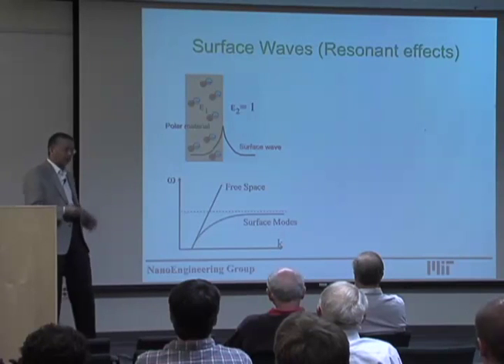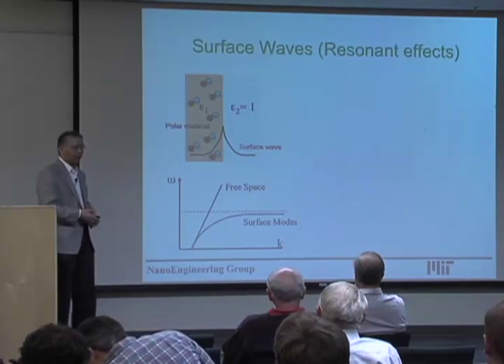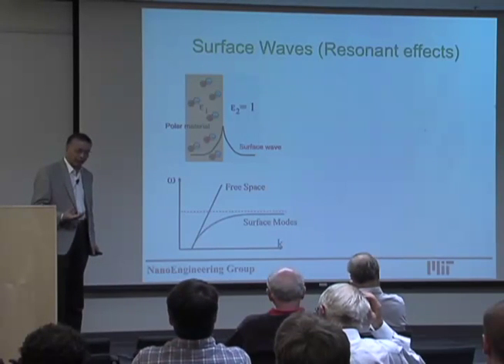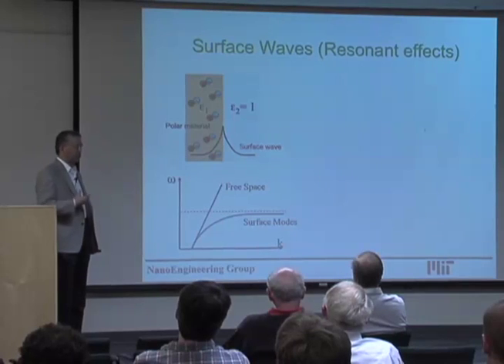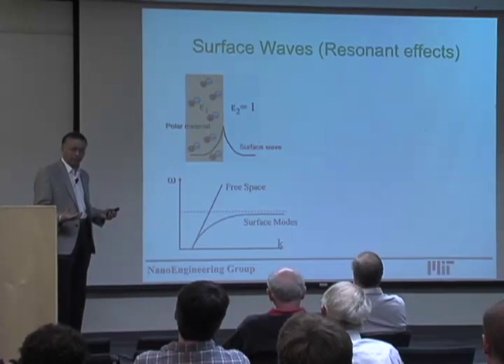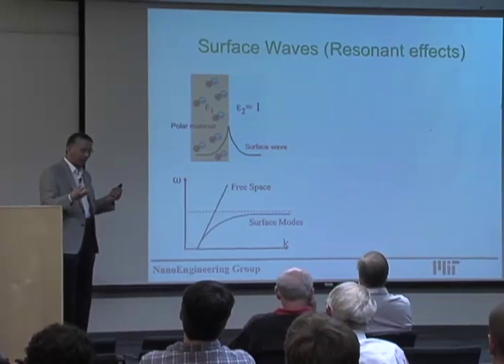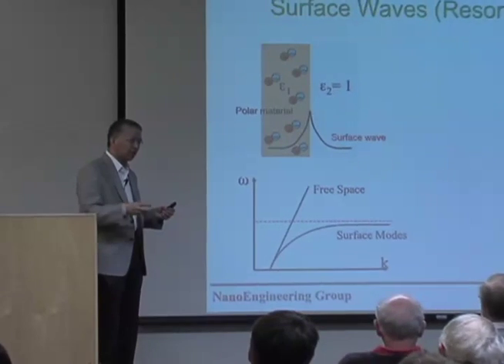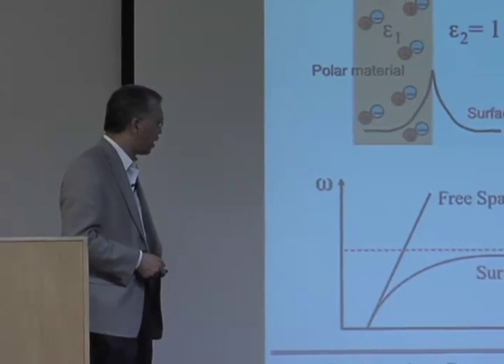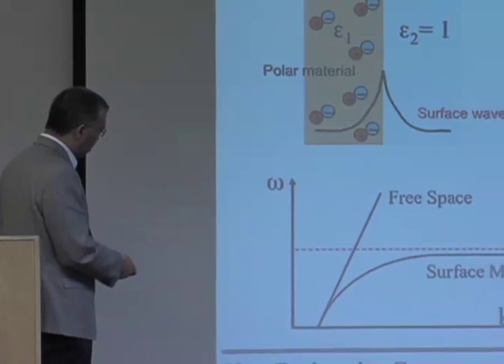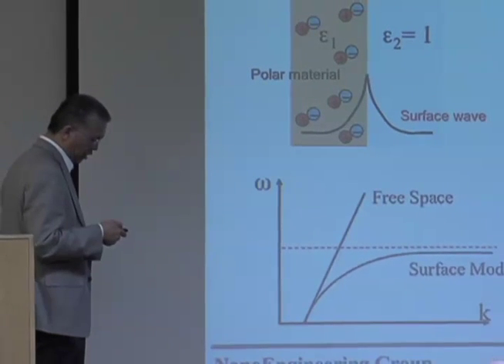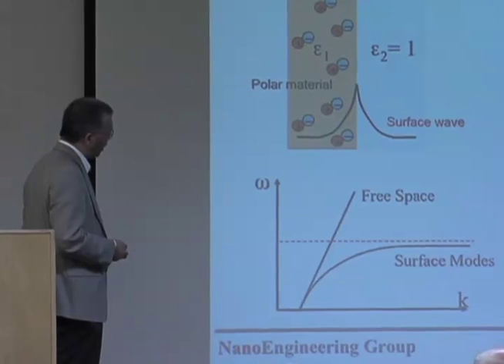And we can look at another situation. This is a surface wave. And again, I'm pretty sure a lot of people are familiar with surface plasmons. And there's a sister phenomenon to the surface plasmon, the surface phonon polariton, which is in a polar material where you have positive ion, negative ion, and the resonance of the electromagnetic field with the ionic vibration gives you the phonon polaritons. And this phonon polariton could have a surface wave that decays on both sides of the interface, same as surface plasmon. And in this case, the dispersion is between the transverse and longitudinal optical phonons, and it can have high energy states.